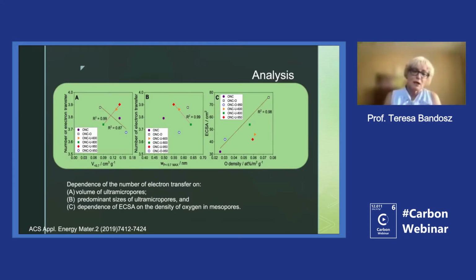on carbons. So we look at the dependencies, and we plot the dependence of the number of electron transfer on the volume of the pores which are smaller than 0.7 nanometers. So it would be that extensive factor, but also as an intensive factor, we have chosen the maximum of the peak of the distribution of the volumes in ultramicropores. And what we found here, that even for the dependence on the volume of the pores, we could see that we had two different slopes. So one was for nitrogen-modified carbon, and one was for non-modified carbon. So it could suggest that they are different mechanisms.